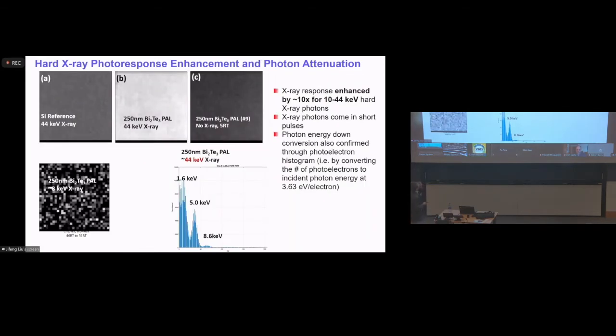So the first thing you want to check is, do you actually get enhanced absorption with the PAL layer? This is the case of a 44 keV X-ray photon with the silicon reference. You can see it looks very dark, but this is one with the 250 nanometer PAL layer. It looks much brighter, meaning the photo response is much stronger. The next question you ask is, is this due to the photon energy attenuation that you promised?